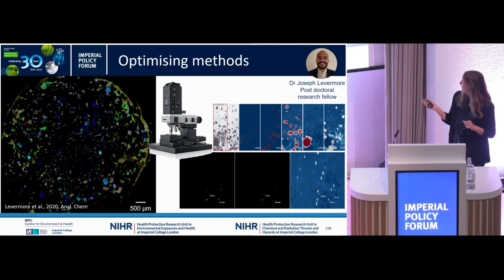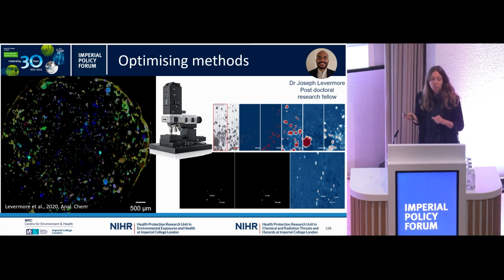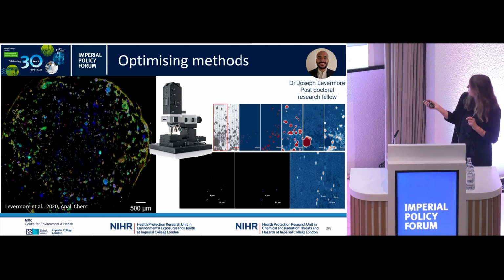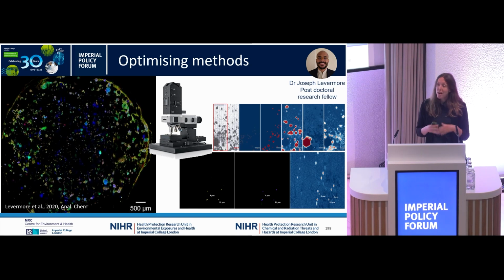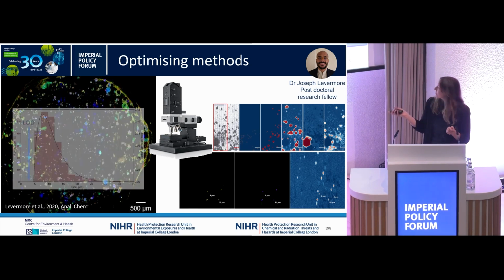And crucially, if we were applying it to a sample that had been spiked with microplastic beads down to 2 microns, we could successfully differentiate them amongst the particulate matter. So this was a really important validation step to know that the method was doing what we wanted it to do, and importantly, that it was applicable to direct analysis in ambient particulate matter samples.